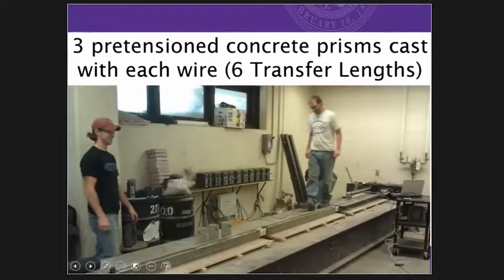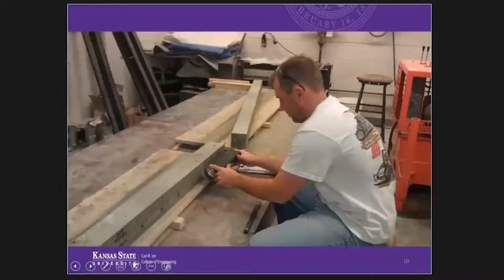And for the concrete, we varied the release strength, we varied slump, and we had data points. We don't actually measure a transfer length. We determine a transfer length by statistically analyzing the surface strain profile that results when we actually detension. The way we develop the surface strain profile, this is one method using a Whittemore gauge, and I'll talk about an automated method a little bit later.